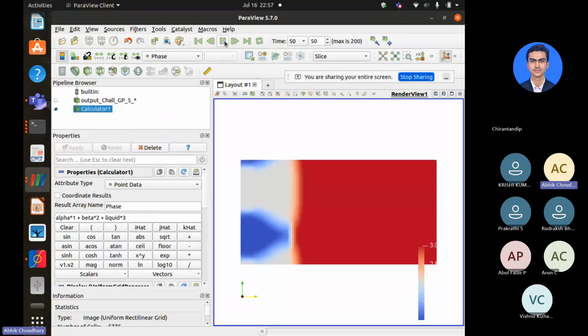Those three phases are going, right? And you see how this shifting is happening? You're moving in the moving frame such that you can do the large simulation. So this is essentially going to the right volume fraction given by the phase diagram, right? Because the connection with the thermodynamics tells it that given this liquid composition, this is the right volume fraction to come out with. So it automatically selects it. If you run a bit longer, it will be steady state.